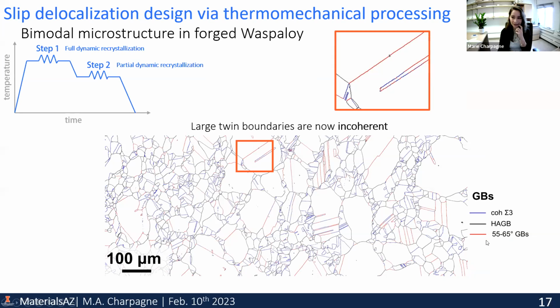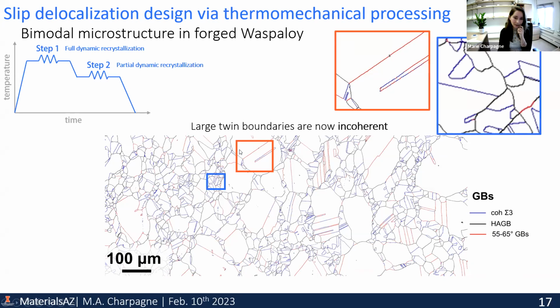And we find that these boundaries, most of them have become incoherent during the step 2, which is good news. Now they're just like random high angle boundaries that are somewhat planar, but not quite coherent anymore. So this is good news for the larger grains. And in the smaller grains, as I mentioned before, the smaller twin boundaries are not as detrimental. They're still coherent, but we think this is not so much of a big deal for shifting or distribution of slip localization events.